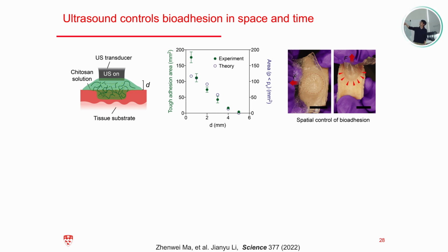Since the effect of ultrasound is very sensitive to the gap, as you can appreciate here, when the gap is too large, you don't get the benefit of ultrasound. But when you get it close, you get the effect of ultrasound. At the same time, we can also use a computational model to simulate the area of the tissue where the solution got cavitated, and we find nice agreement between the predicted adhesion area and the area from our experiment. So that enables us to really control the adhesion by using the ultrasound probe.